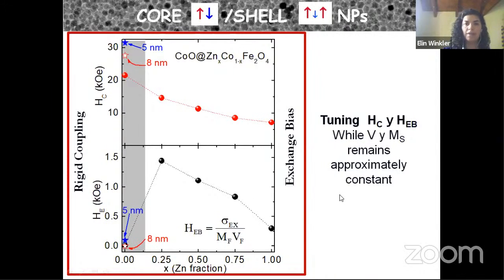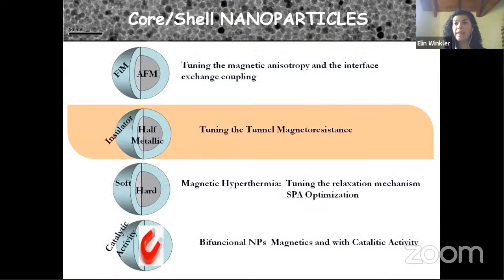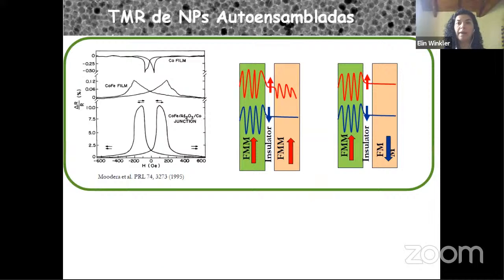So we are going to apply this to the next subject: how can we tune the tunnel magnetoresistance of the systems. Well, a tunnel magnetoresistance junction, for example, is formed by 2 ferromagnetic metallic thin layers that are separated by an insulator layer. The tunnel conduction depends on the magnetic state of these three layers. I mean, the probability of tunnel conduction will be larger when both ferromagnetic layers are parallel, and smaller when the magnetic layers are antiparallel.